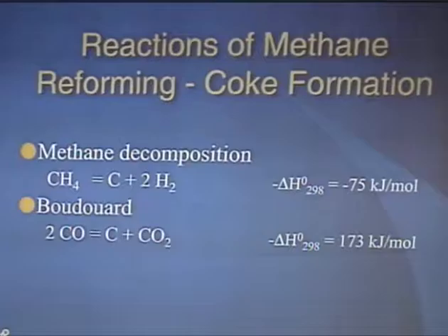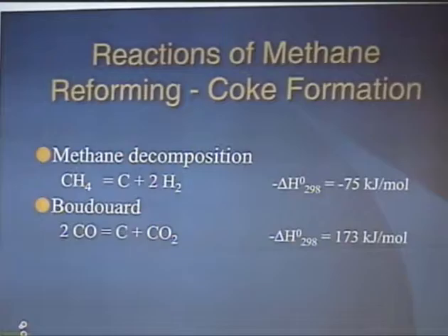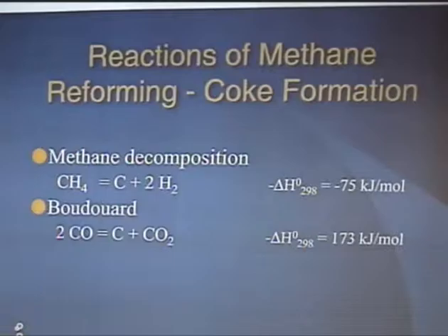However, this process, as we heard this morning, suffers from carbon formation. It can either be from methane decomposition, or it can be from the Boudouard reaction coming from carbon monoxide. And I would also like to add that natural gas usually contains small amounts of higher hydrocarbons, C2, C3, C4, and sometimes it also contains olefins, as also mentioned all morning, due to the treatment of the water gas. So I would also like to include a bit about higher hydrocarbons in my talk.